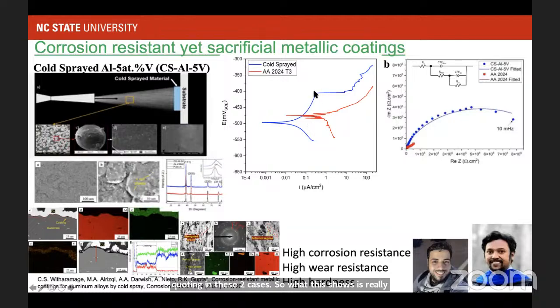So you look at the pitting potential values, they are very different. We did some EIS and things like that, and there's a huge improvement in the corrosion resistance. The wear resistance also improved quite a lot. One thing that is really important to notice here is that if you look at the corrosion potentials, our coated material is corrosion resistant and, at the same time, it is sacrificial.